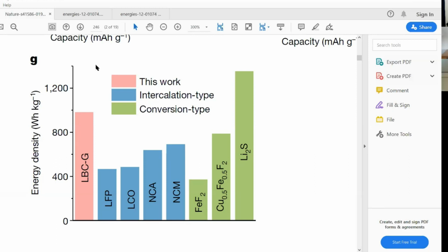theoretically how much energy density we can deliver for our technology here, which is a lithium bromide chloride graphite cathode, compared to these blue bars, which are all for the state-of-the-art lithium cathodes, the intercalation type. LFP is lithium iron phosphate. The big companies like Tesla or other EV companies are trying to use NCA or NCM. So compared to these intercalation types, our cathode's energy density can be even much higher than those, right?